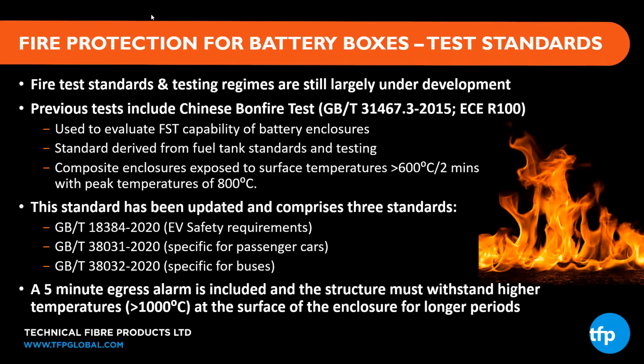The composite enclosures are exposed to surface temperatures of greater than 600 degrees centigrade for 2 minutes, with peaks hitting 800 degrees. Those standards have now been updated. The GBT 38031 is really the most applicable one to passenger cars. And that now incorporates a 5-minute egress alarm, and the structure must withstand higher temperatures, over 1,000 degrees at the surface of the enclosure for longer periods. Next slide, please.